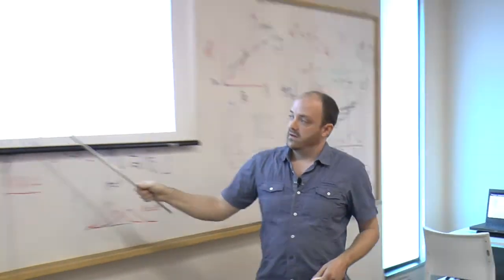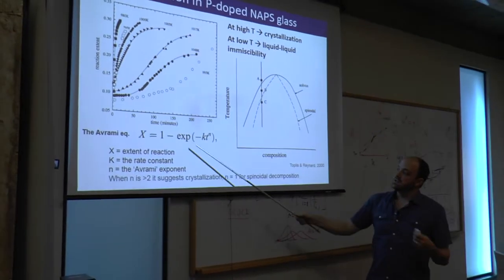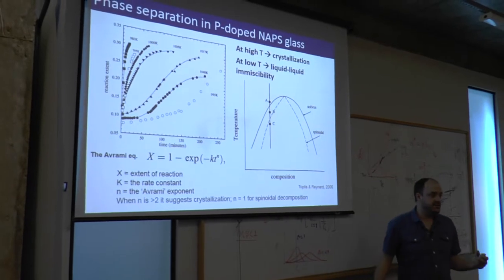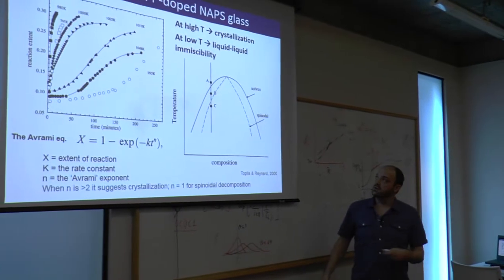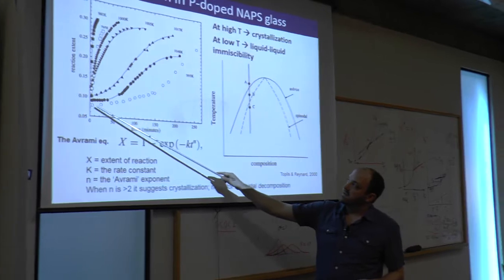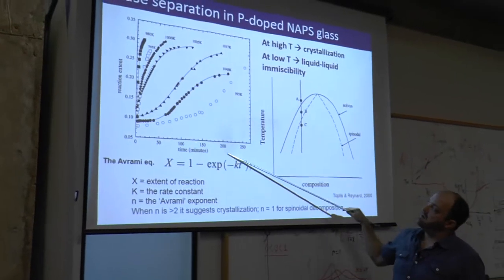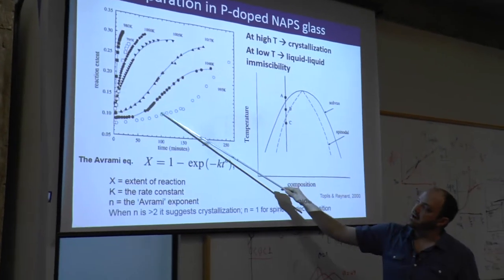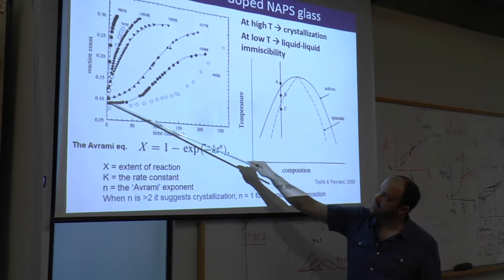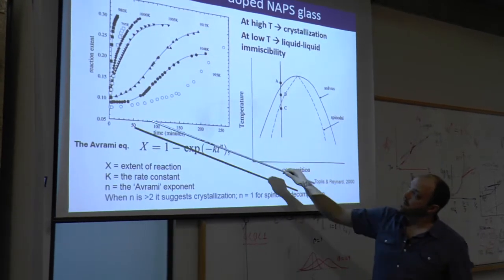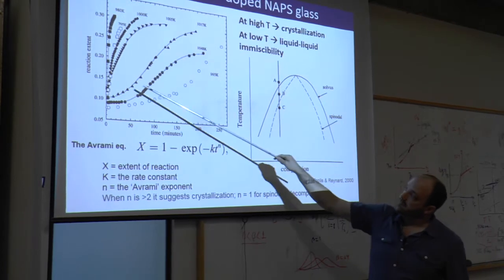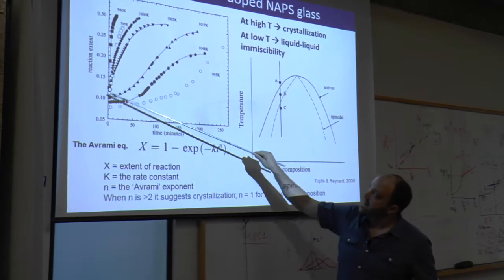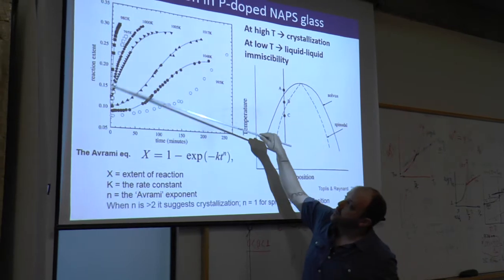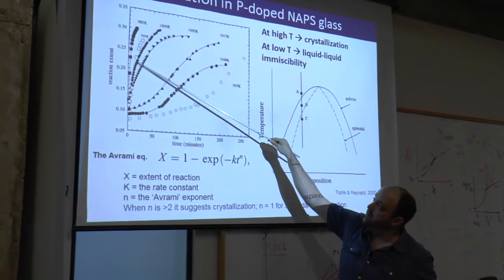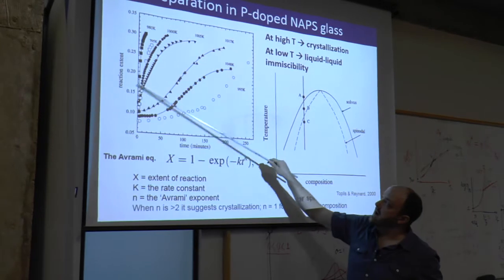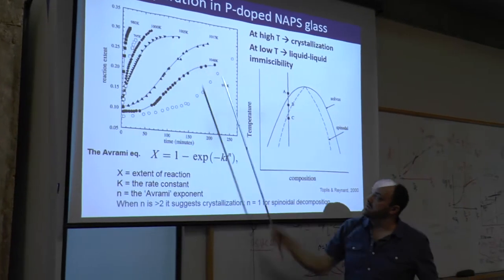They use the Avrami equation here, which looks at the extent of this reaction. In this case, it's the extent of phase separation between those two sodium phosphate phases. And they get quite different curves. So this is time here, and this is different temperatures. At high temperatures, they get a sort of concave behavior of the reaction extent, the phase separation. And here at lower temperatures, they get quite a strong, rapid increase in the reaction at very short amounts of